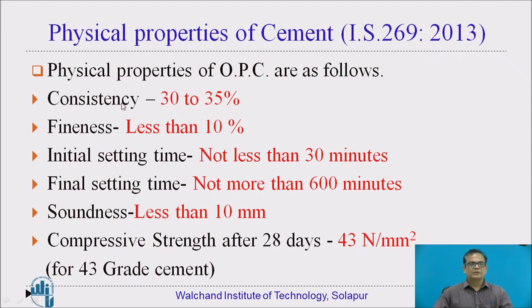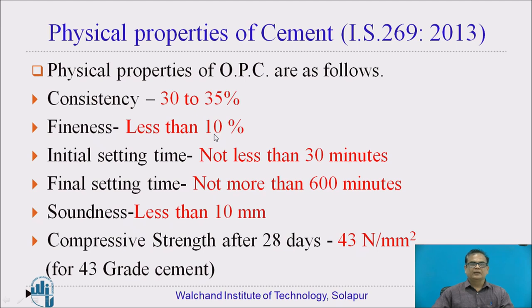These are the physical properties of cement. Consistency is in the range of 30 to 35%. Consistency of cement means its ability to get mixed with water, and 30 to 35% water is sufficient to make a good paste of cement. Then fineness: when sieved through a 90-micron sieve, the residue should not be more than 10%. Initial setting time of cement should not be less than 30 minutes — otherwise, cement will quickly set and will not give us time to place it on site.